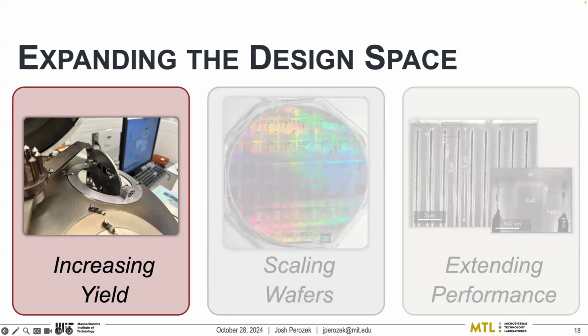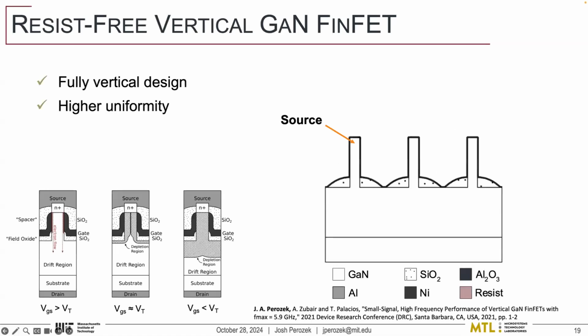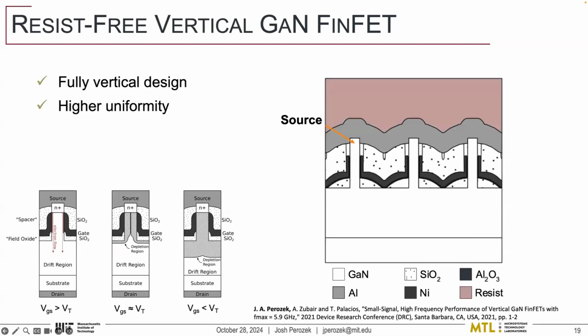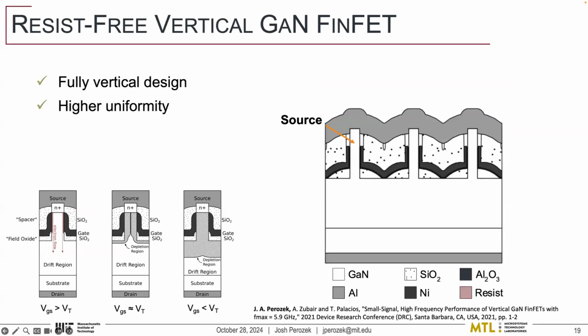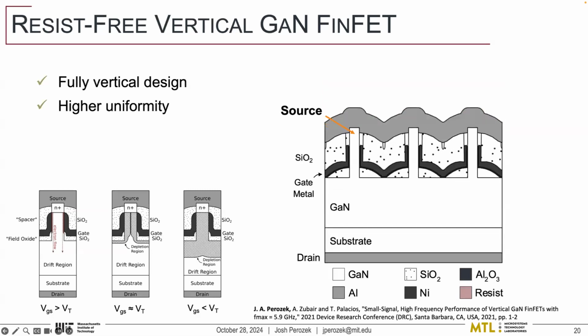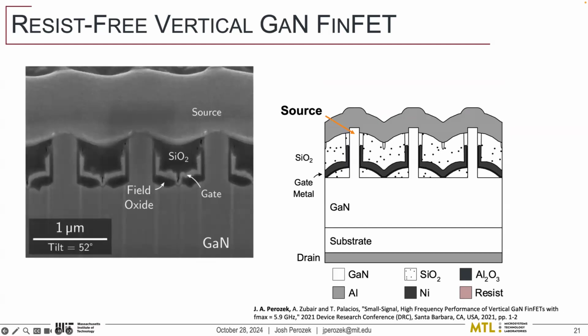So going first into how we can improve the manufacturing of these devices. One of our first attempts, when I first came here, I just tried to replace photoresist with silicon dioxide. We can use PECVD-based systems here to very accurately put on thick layers of oxide that kind of locally planarize the surface. And you can etch this back and make the same FinFETs, which we did.